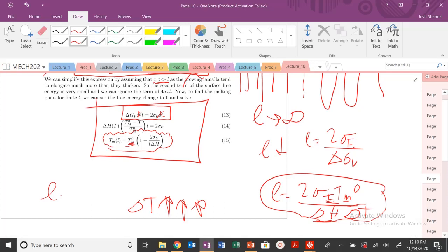Basically, it's saying that as undercooling increases, the critical lamella that needs to be formed is much, much smaller. But if I have a high degree of undercooling, in order to form that lamella, I need more of these favorable enthalpic interactions, these non-specific interactions, because that entropic term isn't coming into play much. So we'll cover more of that in detail in a problem set coming up.